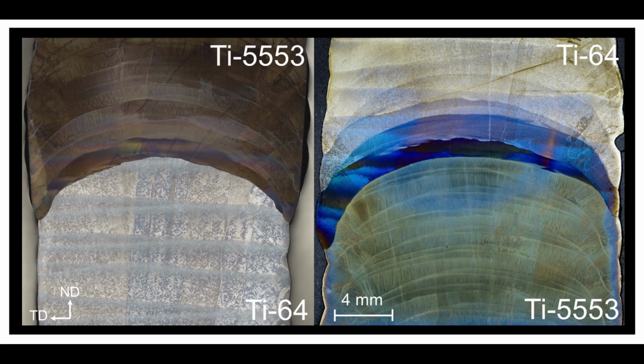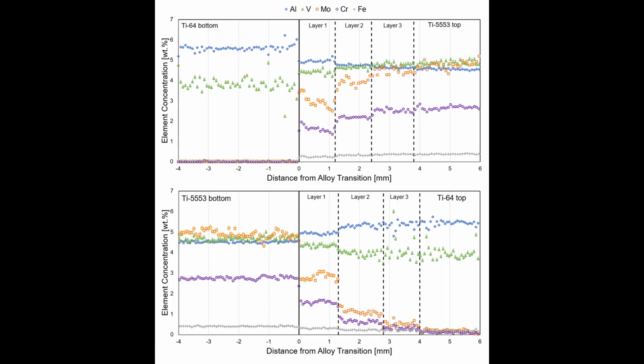In these optical macrographs of the etched samples, the transition regions can be seen in the central areas through the contrast change. We measured the chemical mixing in these areas using electron probe microanalysis, and this plot of the elements as a function of distance shows the stepwise chemical mixing that results from the layer-by-layer deposition technique. Within each step, you can also see some local variance in the alloy composition, where the liquid has failed to completely mix during deposition.